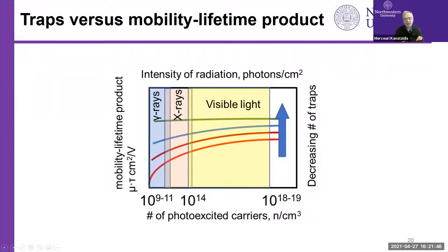What this means is that if you have very few photons, you have to have very few trapping centers to be able to detect the gamma rays, because if your trapping centers are comparable in number to the number of photons falling in, which means the number of carriers generated are also comparable in number, you may get low response because of a lot of trapping. But this situation may improve on the same material if you have X-rays, because you have more photons and therefore more electrons in principle than the trapping centers that you may have. And so in that case, you may see better response. And with visible light, it's always easy, even more photons, and you can always overcome the number of trapping centers. And so this is a thing to keep in mind. The mu tau may be changing as a function of number of carriers.